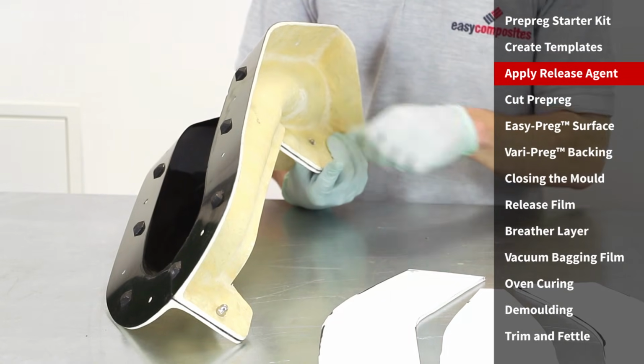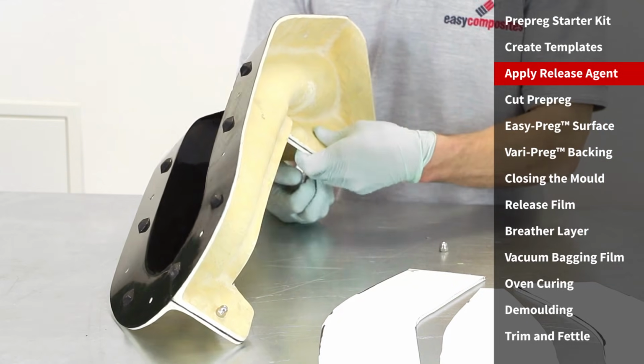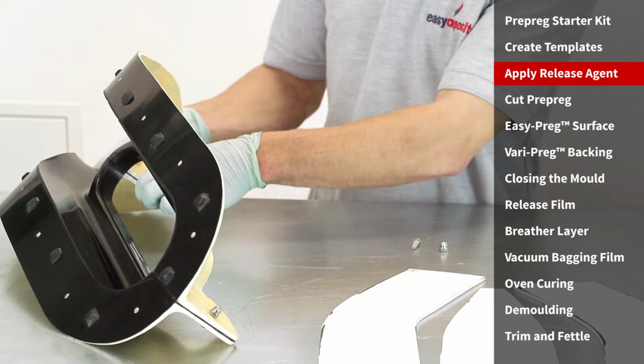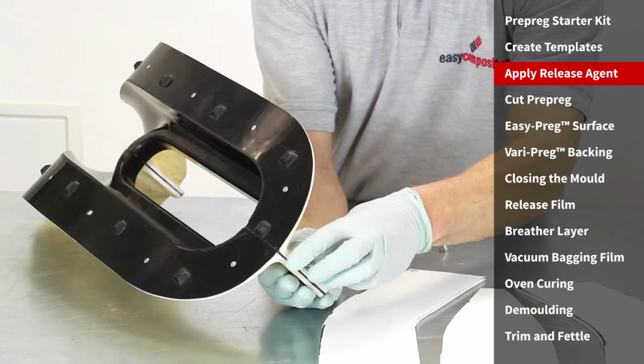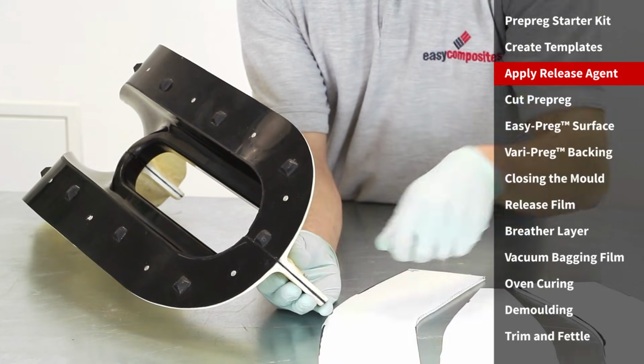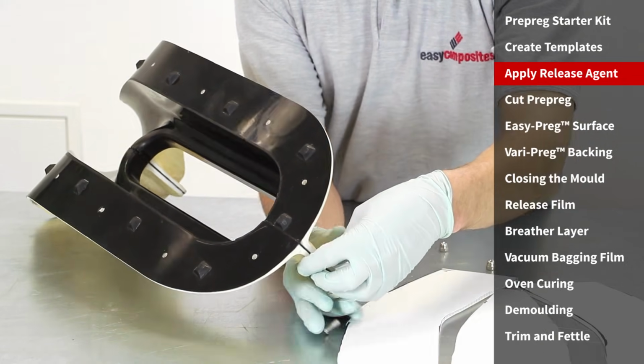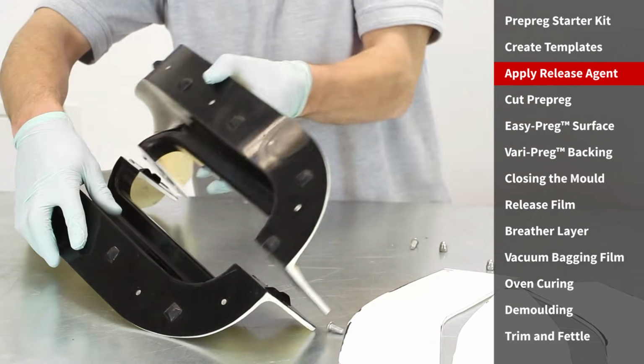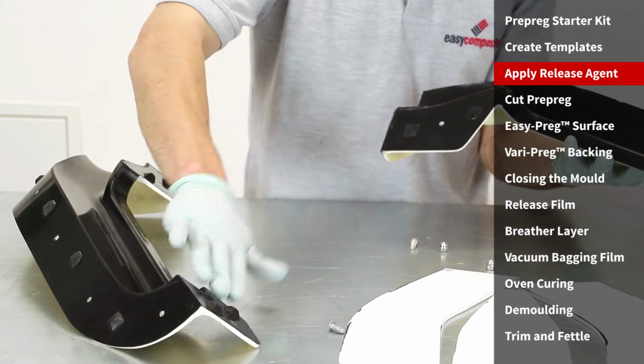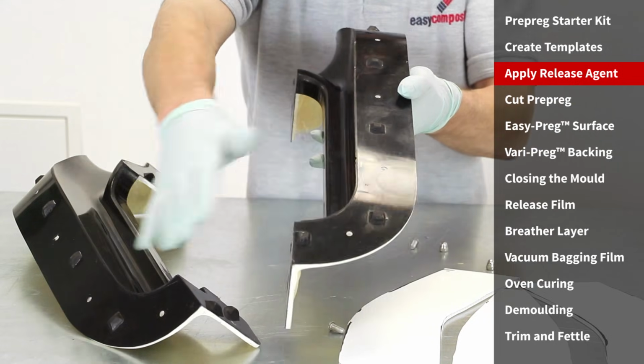Now, when this part is actually vacuum bagged, some of the resin will get driven between the parting lines. So it's equally important to get release agent onto the flanges of the mould as it is onto the main surface of the moulding. So we'll be applying the release agent right over the surface, over here, and also these areas here and here.